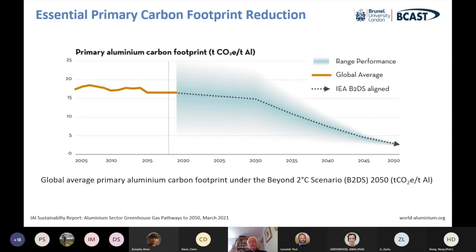The International Energy Agency, the IEA, that's the one, have really suggested that the aluminium industry really needs to reduce the carbon footprint of primary aluminium from its present average level of around 16 tons per ton of primary aluminium produced to around 2 tons per ton. So they're not really saying that primary aluminium has to get to zero. And the aluminium industry is being allowed this